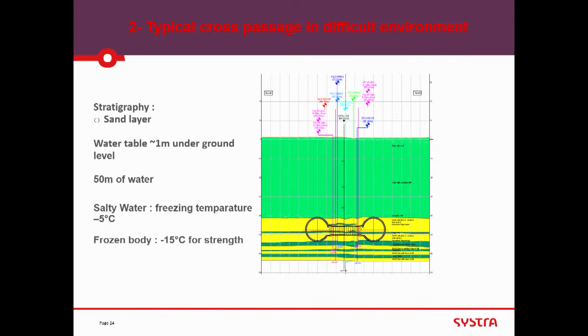So in this case, what we were looking for is a frozen body temperature of -15. A lot of compressive UCS tests were done to find out that the frozen soil at -15 had the required shear strength for stability when we were excavating the tunnel. But in this case, we had sand with 50 meters of water, 500 kPa water pressure, a lot of water pressure in sand. So we cannot play with it.